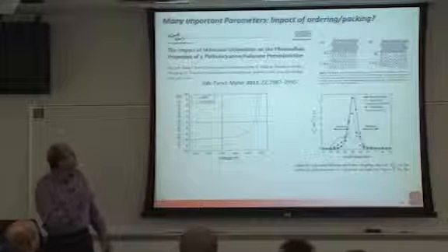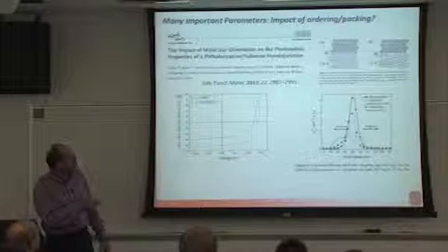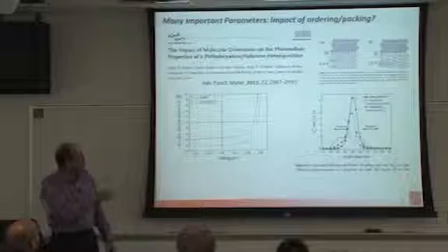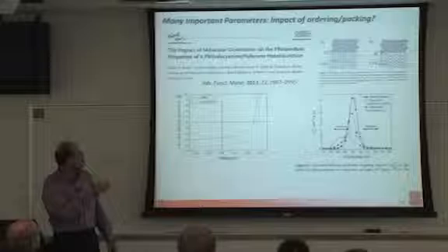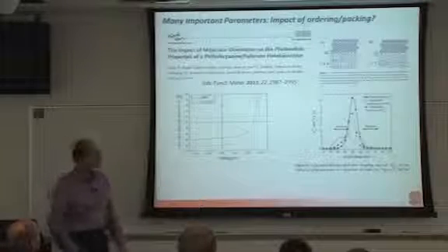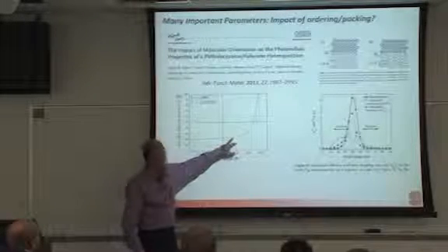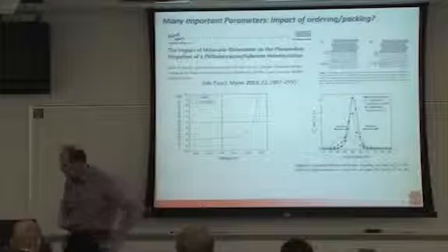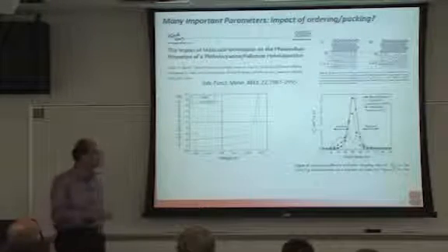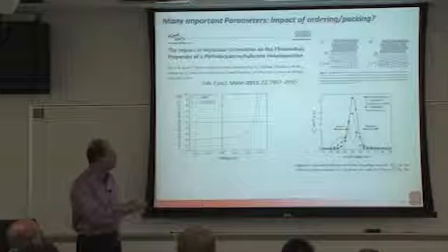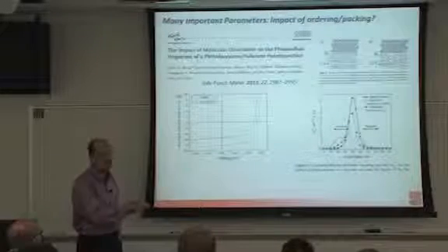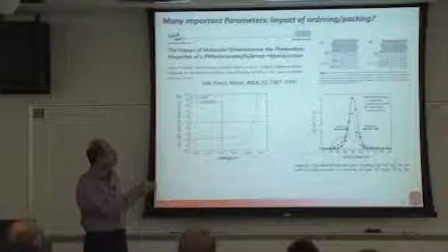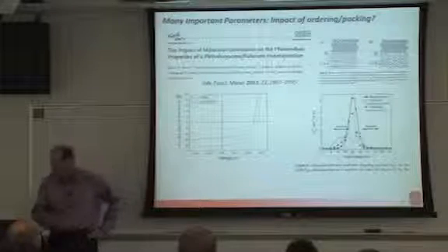If you look at a phthalocyanine fullerene heterojunction and you control the orientation by growth on a different substrate, you see quite a difference in performance. And then there are theoretical studies in the Brédas group that show that indeed there's a difference between face-on and edge-on in terms of the charge separation efficiency at this versus this interface.